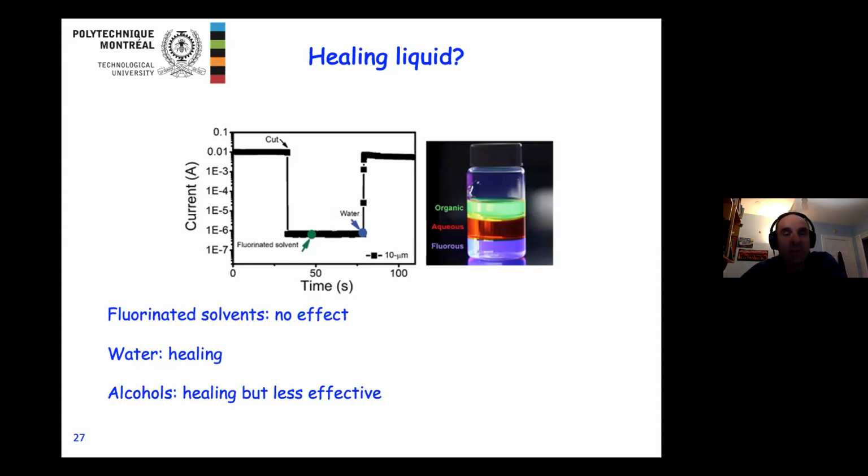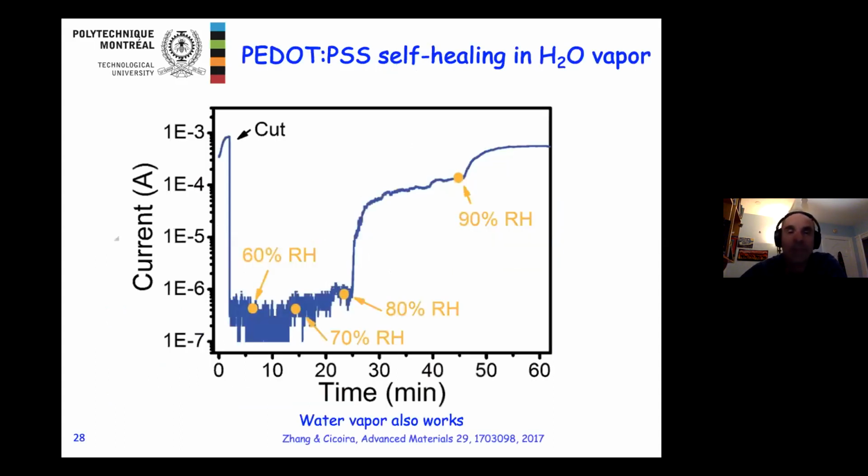We also looked at several liquids, just to be sure that it was not a physical effect of moving materials. We took the most inert liquids for our system, which are fluorinated solvents, and we didn't see any effect on the healing. We used some alcohols and observed a weak effect, but the solvent that works best is water.